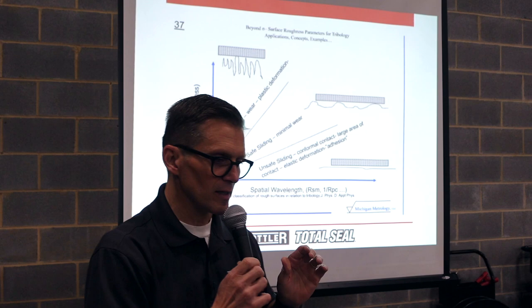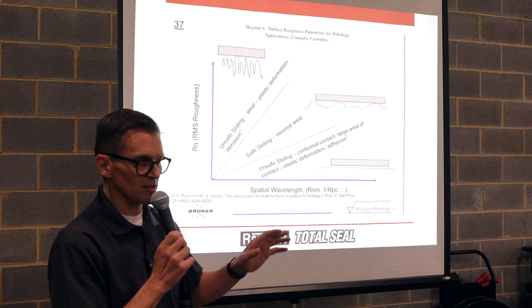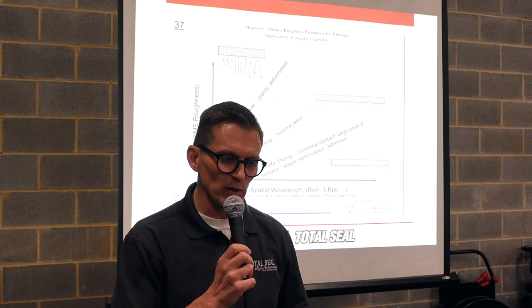Because what you want here is Goldilocks and the three bears. One of my favorite chemical analogies, and it works in engines too. You don't want it too rough, because that's gonna cause abrasion, but you don't want it too smooth either. I remember back when I was working at Gibbs, we got into polishing the camshafts and everything. We got the camshafts to an RA of less than 2, and we burned all the camshafts up. Why? Because we didn't hold enough oil. We made it too smooth. There was no oil retention anymore. So you gotta have the right amount of roughness in there. Again, that Goldilocks and the three bears.